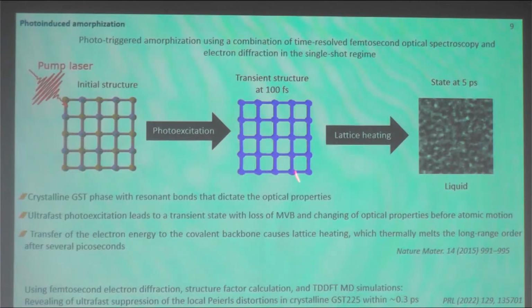the system lost this, and then afterwards, due to the energy transfer to the electrons and to the lattice system, it heats up locally and then melts. So by the process of lattice heating, the system transforms to the liquid and then to the amorphous state. This occurs on a time scale of around 5 picoseconds. So this is also a non-thermal process.